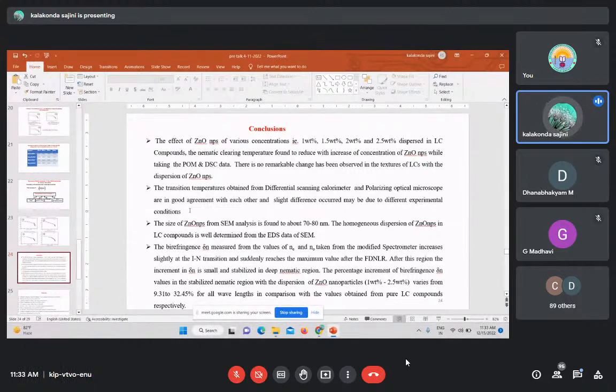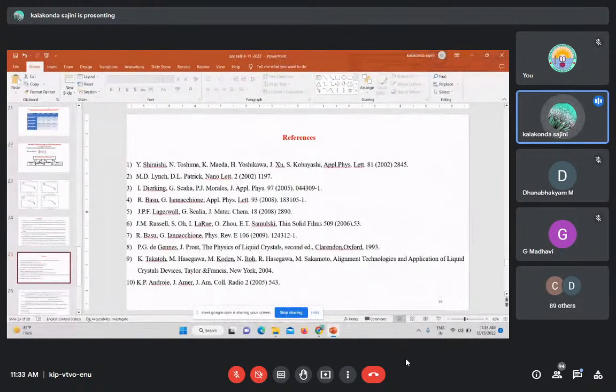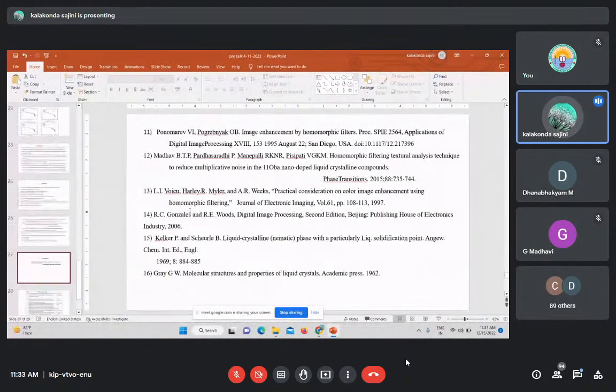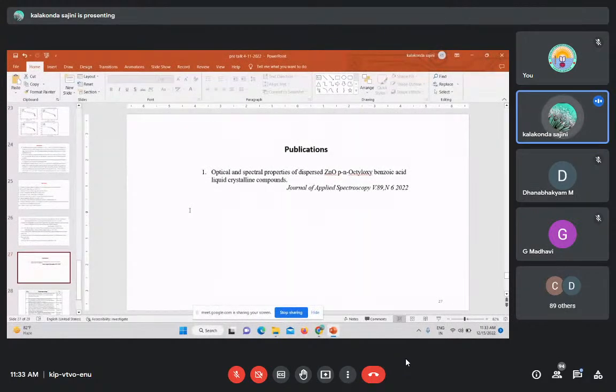We can find that the birefringence increases in the I-N transition, suddenly reaching the maximum value. After this, the percentage of increment of birefringence values stabilizes in the nematic regions of ZnO at various weight percentages, increasing from 9.3 to 32.45 percent in comparison with pure LC compounds respectively. And these are some of the references I have taken for doing this work. And I have published this paper in the Journal of Applied Spectroscopy.